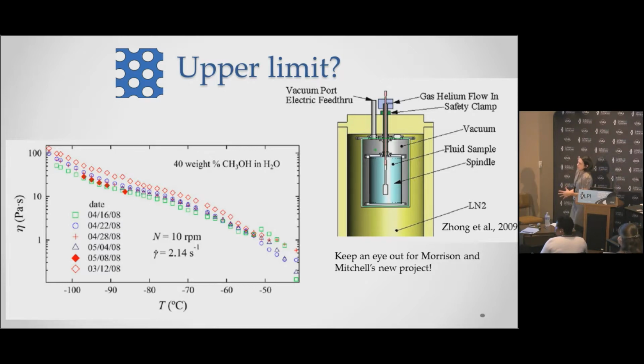And this is just one. I mean, Jeff has done a lot of work on this. The group at JPL has done a lot of work, so I just picked one of the images, but showing here it's with temperature getting warmer, but that would also equate to melt fraction, a nice gradual decrease in the viscosity with increasing melt fraction.